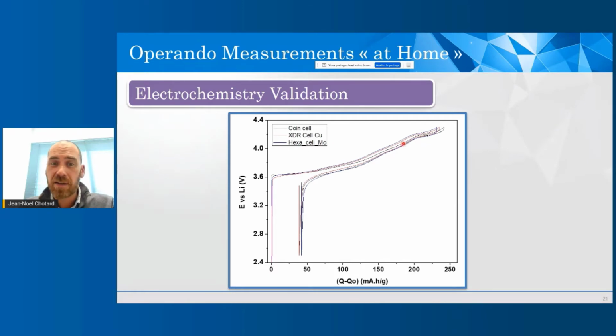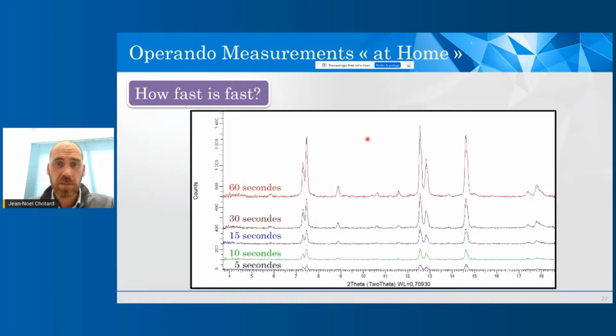And as you can see, they are all one on top of the other, which means that our electrochemistry is really reliable from one cell to the other. So we want to measure fast, but how fast is fast? We did several trials, and we've been able to measure from 60 seconds down to 5 seconds, as you